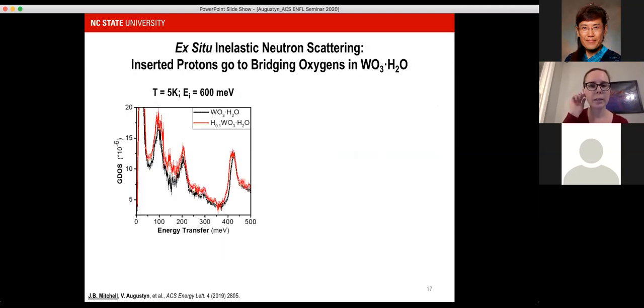The other thing that we did was we actually did ex situ inelastic neutron scattering, also at Oak Ridge National Lab. This is a technique that's wonderful for studying the location of protons and being able to verify with density functional theory. What we found from these results is that the protons go to bridging oxygens in the hydrated materials. So for example, this is an inelastic neutron scattering result.